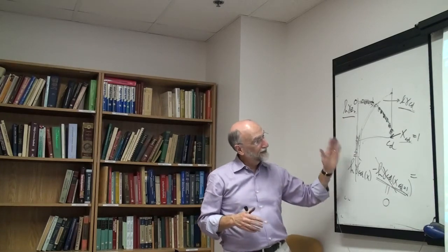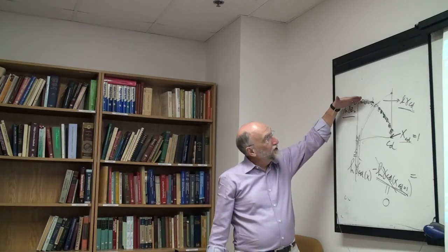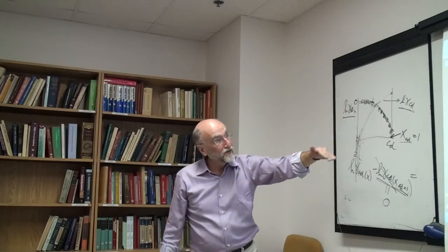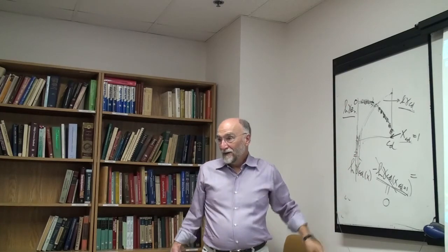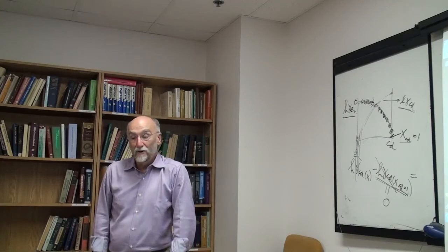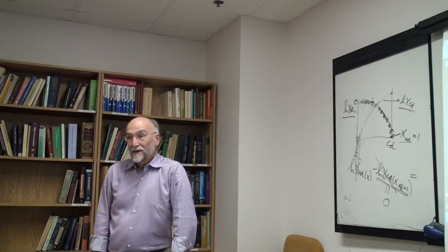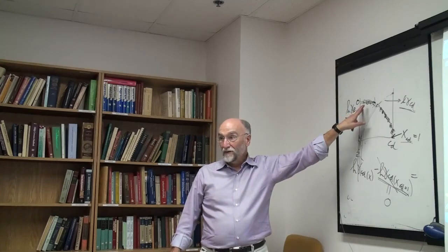So you've got to really think about what is happening. Effectively, this is what the computer is doing. And you've got to have really accurate measurements of this liquidus of aluminum. Even if you have a proper endpoint for calcium, if you're getting the activity of aluminum from the liquidus, any slight errors here are going to have a really big influence. And you find that the activity coefficient of calcium, if you look at the literature from different measurements of the activity of aluminum, can vary by 3-4 orders of magnitude, which is rather important. If you're making aluminum, you're worried about calcium vapor pressure and so on. The only really good way to get it is to actually measure the activity of calcium, not the activity of the other thing, and then differentiate it.